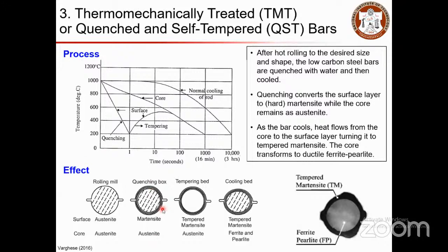And when it is being kept in the tempering bed, this is going to slowly emanate the temperature from the surface to the inside. So the martensite will become tempered martensite. And still your core will remain as austenite. When you do a cooling process, my tempered martensite will still be the same and slowly the coolness from the surface is going to get disseminated through it. So the core becomes ferrite-pearlite. So when you cut and look at the cross section of your TMT, you'll have the inside ferrite-pearlite phase and then the outside tempered martensite phase. So this is what we call TMT, right?